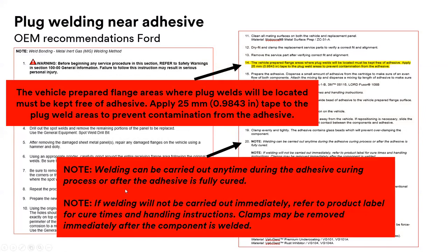Now they say, and this brings up a good point, because Ford says in their information, welding can be carried out anytime during the adhesive curing process or after the adhesive is fully cured. Now 3M, we do not recommend welding through our adhesives when they're cured. And if you've ever done that and cut them apart, you'd see why. Because once they're cured and you weld through them, it just turns it to charred, burnt adhesive and does not work well.